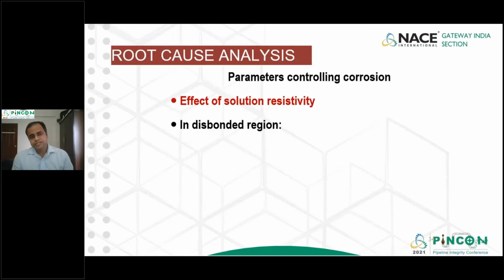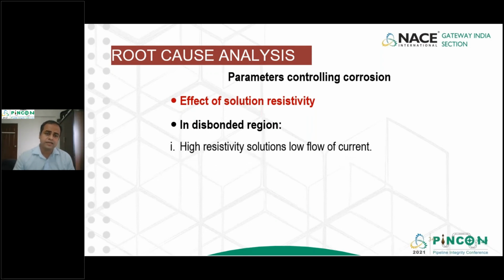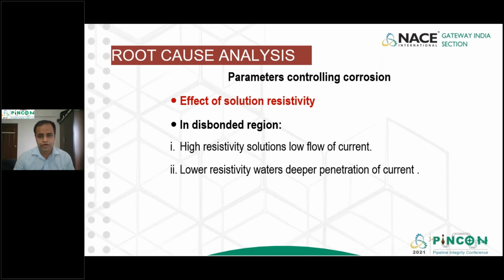Now, we'll consider the second factor, that is the solution resistivity. Now, you all must be aware that resistivity is nothing but the opposite of conductivity. Now, in case of cathodic protection, all that matters is the flow of the ions. The higher the resistivity, the lesser will be the flow of current, and the less impactful will be your cathodic protection systems. So, the low resistivity waters gain a deeper penetration into the crevice and thus achieve cathodic protection inside the crevice at a much faster pace, thus ensuring a correct cathodic protection implementation.